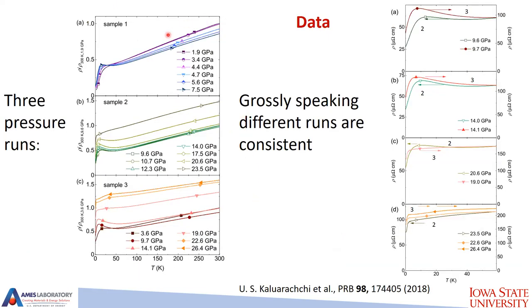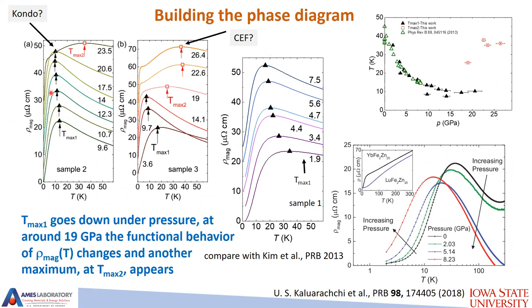So what did we get? Well, we had pressure runs. We were following the maximum in resistivity, or actually in the magnetic part of resistivity. These three runs effectively are the same if you don't pay attention to absolute values of resistance or resistivity. So what happens with this maximum? Now I'm showing the magnetic part of resistivity, up to subtraction of that of the lutetium counterpart at ambient pressure. This maximum, which is usually a proxy for the Kondo temperature, goes down as expected and consistent with our initial data. So that's how it goes.